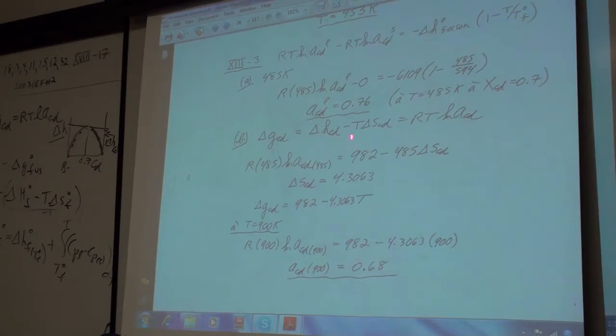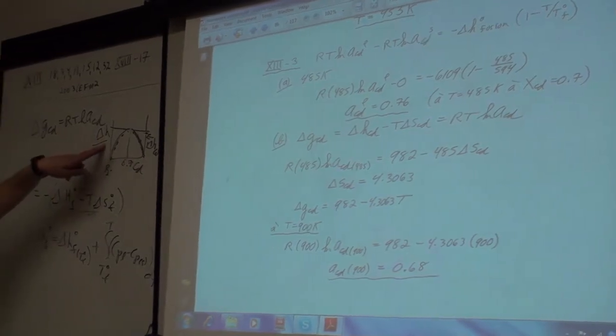Okay, so now I have this equation here, delta G equals RT log activity, as a function of T. I have the delta G at one temperature, and I have delta H. So I can calculate delta S, and I get delta G as a function of T. So now I can calculate delta G at any temperature, and I can get the activity at 900 Kelvin. I've made another assumption, of course. I've assumed that the heat of mixing is independent of temperature.